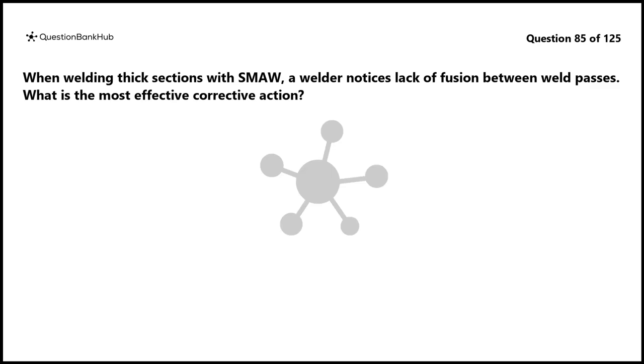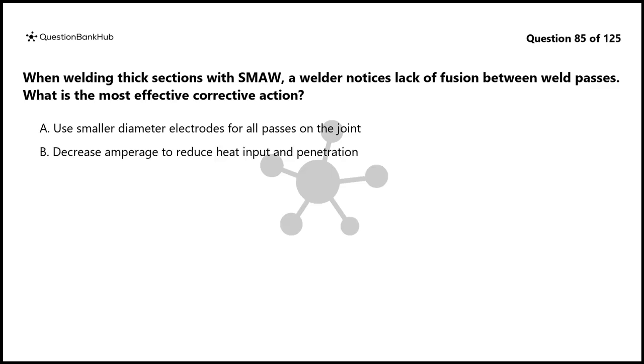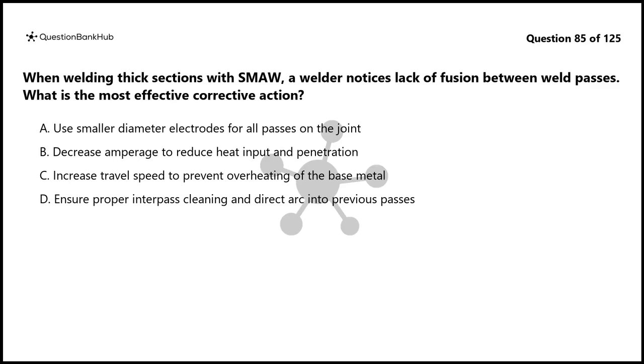Question 85. When welding thick sections with SMAW, a welder notices lack of fusion between weld passes. What is the most effective corrective action? A. Use smaller diameter electrodes for all passes on the joint. B. Decrease amperage to reduce heat input and penetration. C. Increase travel speed to prevent overheating of the base metal. D. Ensure proper interpass cleaning and direct arc into previous passes.